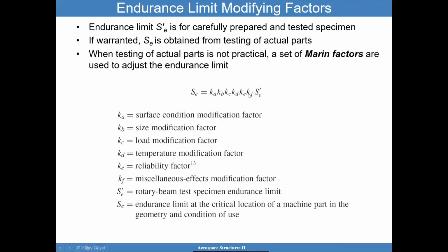And then KF can be miscellaneous values. But note, the Se prime is usually a rotary beam test specimen. And Se here becomes the endurance limit at the critical location of the part in the geometry and the condition of use. So again, very two different values. Don't get confused this one with that one. And don't go running with the value from the test specimen. Try to make sure you consider the Marin factors.